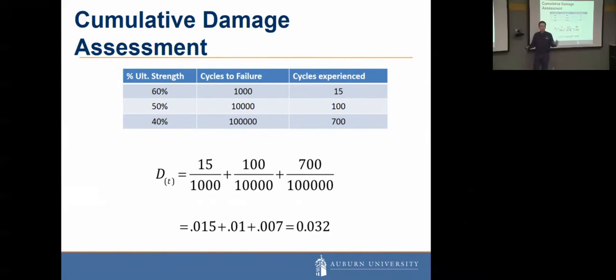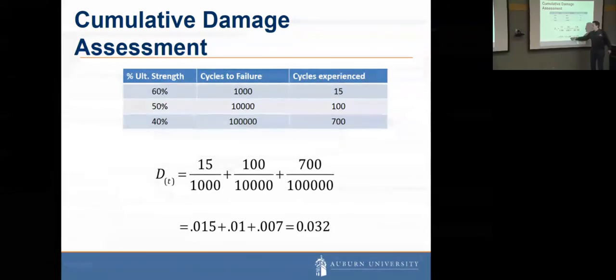The way that we can add this up and get to a single measure of cumulative damage is to take the 15 cycles experienced over the 1,000, add the 100 over the 10,000, plus 700 divided by the 100,000. And just that simple calculation can get us to some measure, and think of it as 3% of the way to fatigue failure. Notice that we've had people focus on repetition, for example, as an independent risk factor. Well, if we look at repetition, this 700 would be the worst situation, right? But because so many more cycles are allowed before failure would occur, that's actually about half the risk associated with the 15 cycles at 60% ultimate strength.